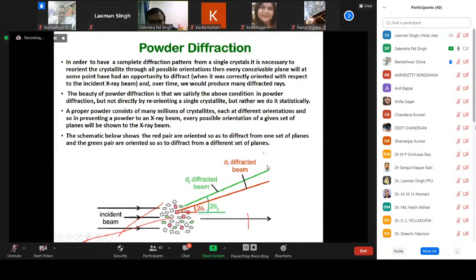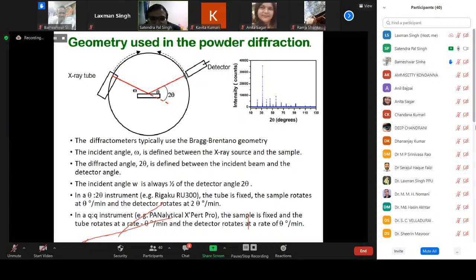In order to study this kind of phenomena, the diffractions, all the instruments use a particular geometry, called the Bragg-Brentano geometry. These diffractions use the Bragg-Brentano geometry, in which the X-ray is incident at angle omega, and this omega is equal to theta, and the detector is at 2 theta. The incident angle omega is the angle between the source and the sample. This is the sample, this is the X-ray tube, and this is the detector. So the X-ray is incident on the sample through the angle omega, and it is recorded by the detector at 2 theta. This 2 theta is the angle between the incident source and the detector.